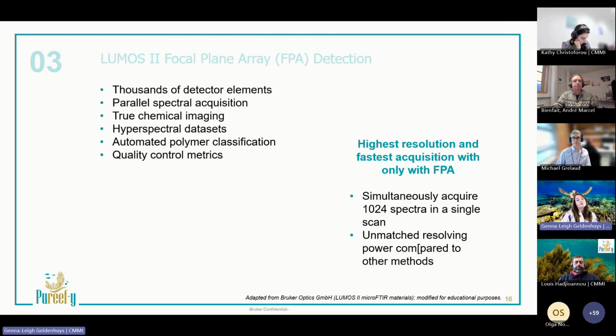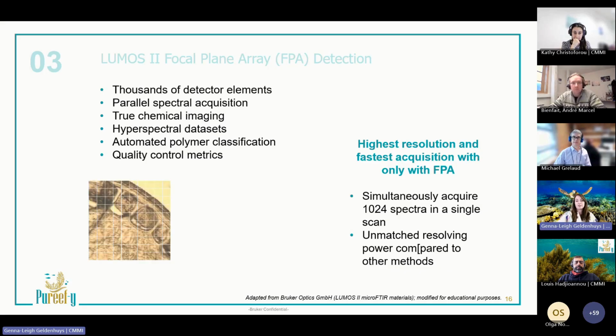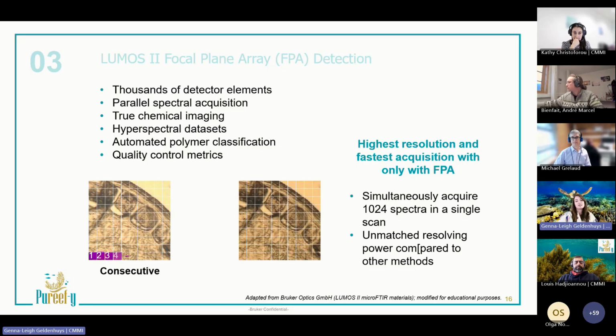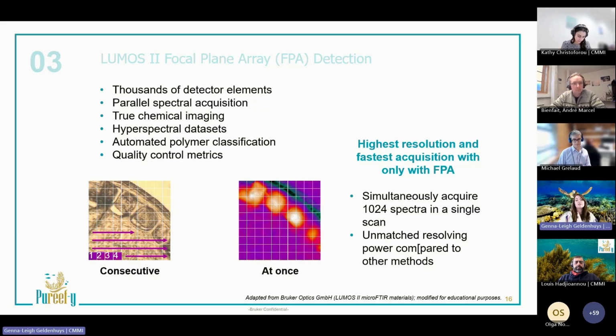So now let's get into the key technologies that have recently advanced microplastic analysis, one of them being the focal plane array detector. So instead of measuring one point at a time, an FPA consists of 1,000 detector elements that collect spectra in parallel, allowing us to acquire over 1,000 FTIR spectra in a single scan. This enables true chemical imaging where every pixel contains a full infrared spectrum, resulting in hyperspectral datasets. Now, when we say hyperspectral datasets, we're actually saying millions of FTIR spectra. So instead of isolated measurements, it's a no-brainer.